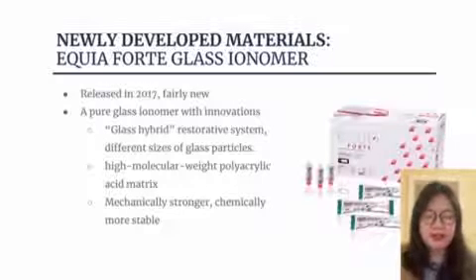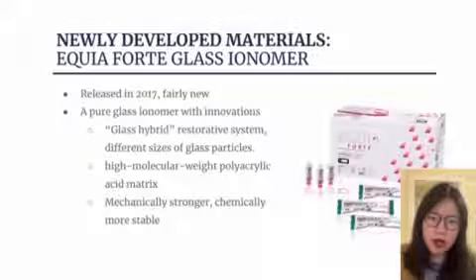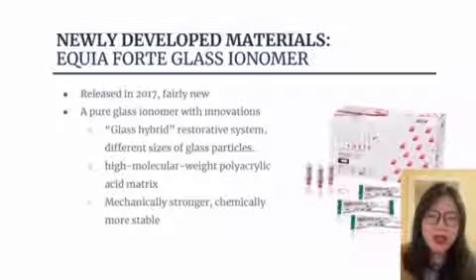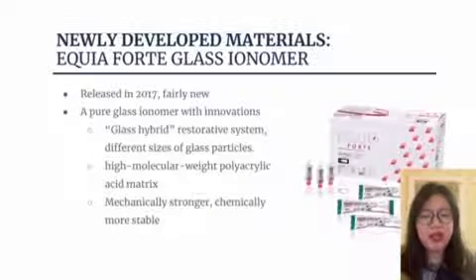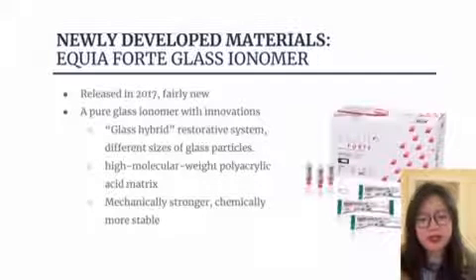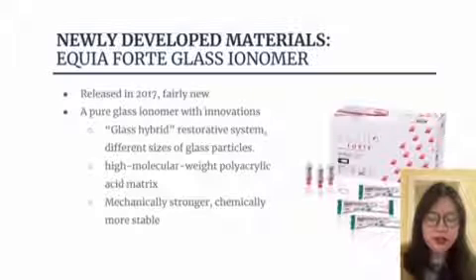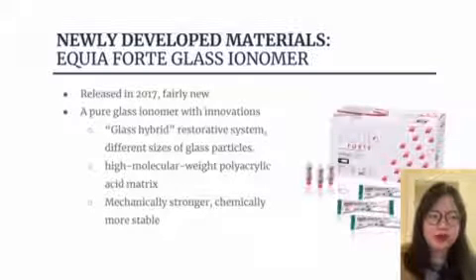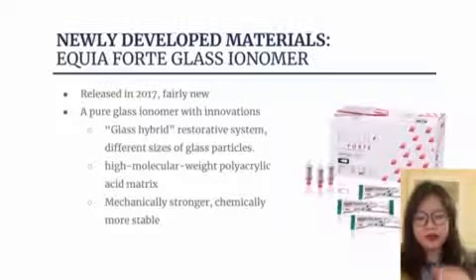Even more recently, in 2017, a new material called Equia Forte was released. Compared to resin-modified glass ionomers like Fuji 2LC and Activa Bioactive, this material is a pure glass ionomer. However, they introduced a new technique called the glass hybrid restorative system — they use different sizes of glass particles when designing the glass ionomer, and also include a really high molecular weight polyacrylic acid matrix. This is supposed to boost wear resistance and make the material mechanically stronger, chemically more stable, and they also claim it has a higher fluoride release.